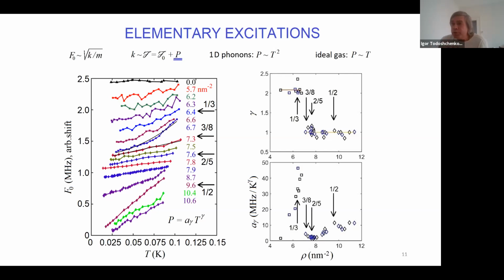But we can also measure thermodynamical properties of helium. This is because the center of frequency depends on the stiffness of the spring constant, which in turn is proportional to the tension of the tube. And the pressure of helium contributes directly to the tension. So by following the resonant frequency far from the transition, we follow the pressure as a function of temperature. Basically this is additional pressure due to adsorbed helium, arbitrarily shifted.